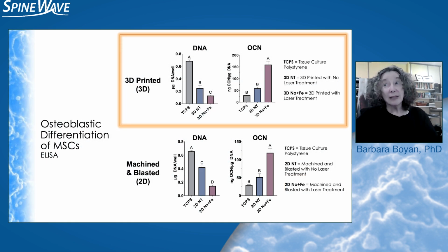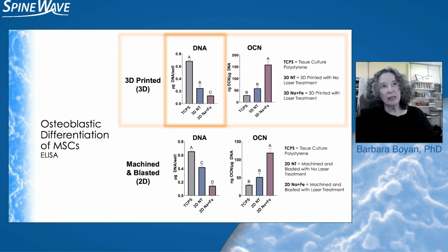Okay, so it does matter. And now we have cultured human bone marrow stromal cells, the ones that are going to migrate on when this implant is placed in the spine. And you can see here again that the DNA goes down on the surfaces as we move from plastic to titanium. This is a non-treated surface, but it's titanium, so the cell number goes down. But as we treat the surface, the cell number is reduced even more.